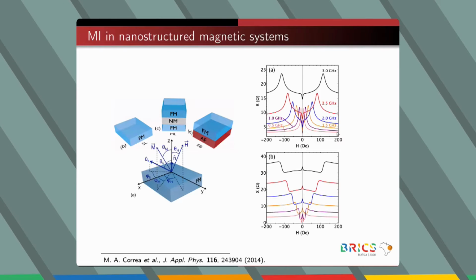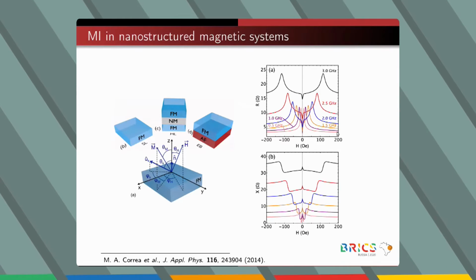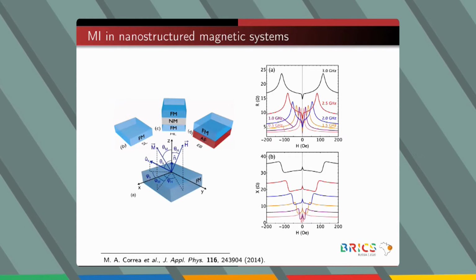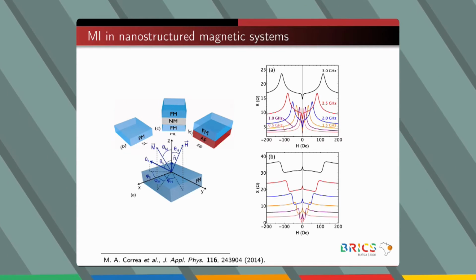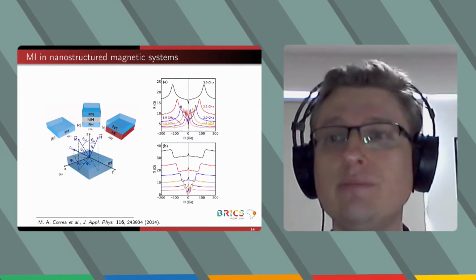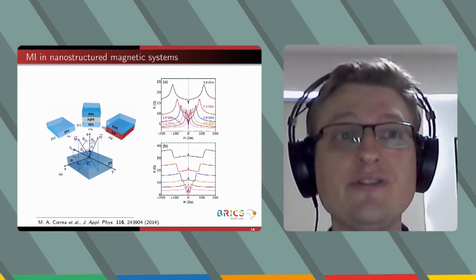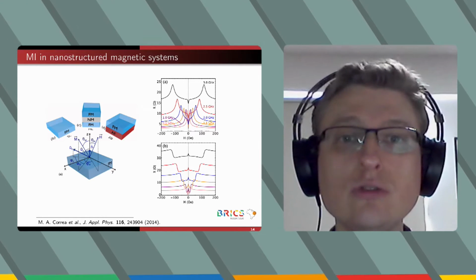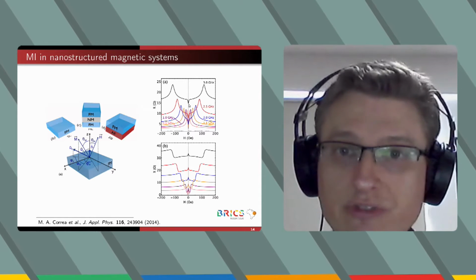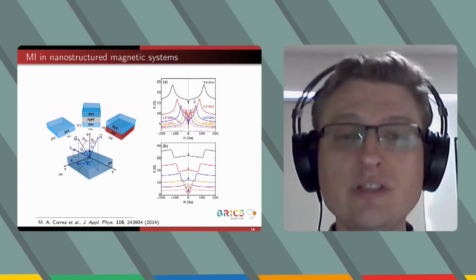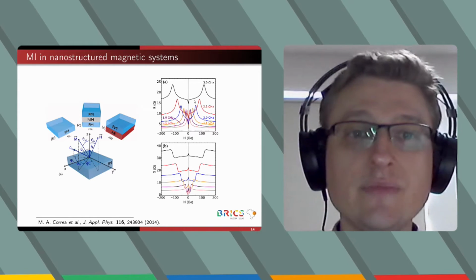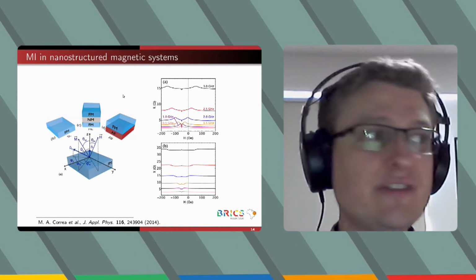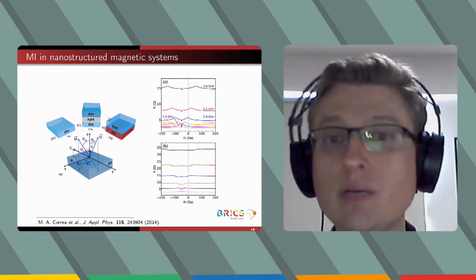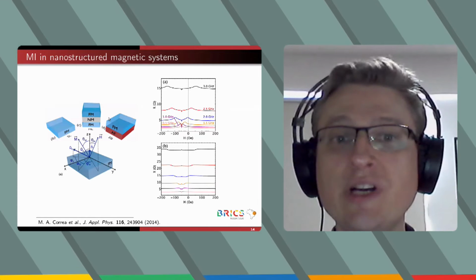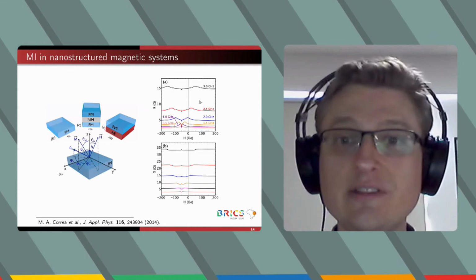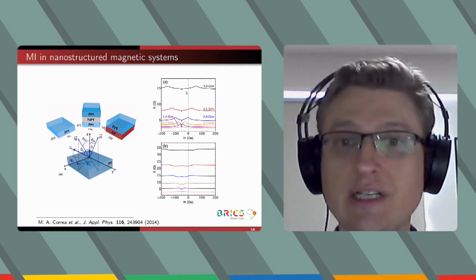Films and multilayers with uniaxial anisotropy often present symmetric curves with dependence on field and frequency. The idea here is to understand the shape of the curves and relate them to the mechanisms responsible for the impedance changes. However, it's important to notice that the curves do not show a linear response at low fields, which can make difficult the application of these materials in devices. However, when considered a system composed by a ferromagnetic layer coupled to an antiferromagnetic material, we're able to shift the curves in field, thus obtaining such linear behavior around zero field.